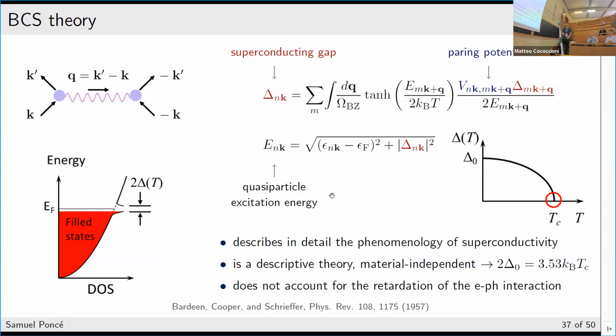It describes this phenomenology of superconductivity, but it's actually material independent. You can see it because at 0 Kelvin, at least, you have a direct relationship between the size of this band gap and the critical temperature of the material. So this means that two different materials that have the same critical temperature will also have the same band gap. And obviously, this is not the case. Different materials can give you different superconducting gaps.